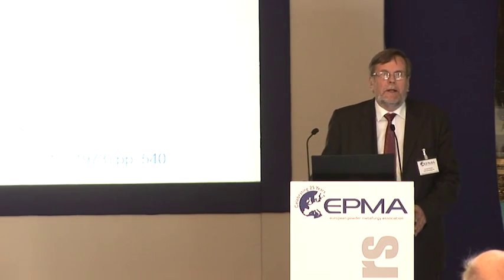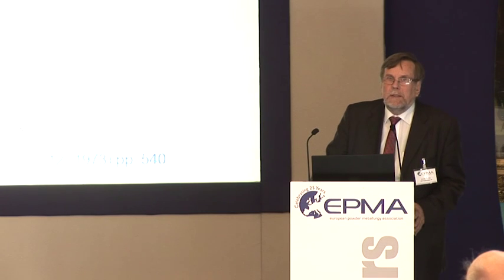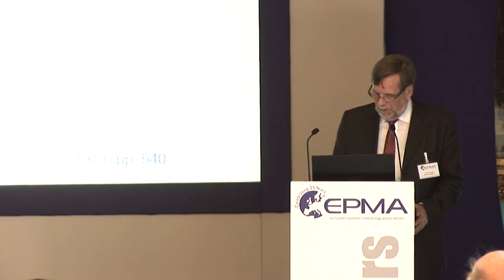This shows the work from Kennametal, if it's possible to read. You can see the advantages of pore closure. Take away the last percentage of pores in cemented carbide, and you can see that the transverse rupture strength is increased by 20-30%. And this was further the basis for the development of the sinter-HIP process, which Leo Prakash has described.